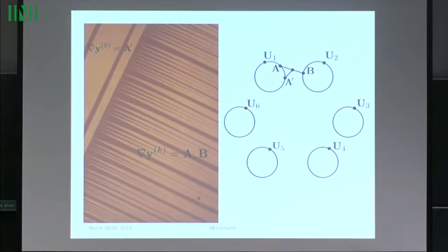And indeed you find exactly one. That's this A prime. And so I can drive the energy in this transition layer to zero, I can write a minimizing sequence, and that's the physical realization of that minimizing sequence. The volume fraction here will be correctly predicted, and so forth.